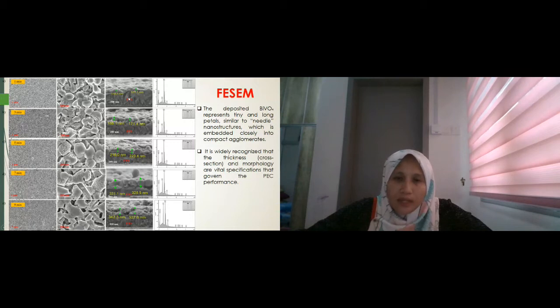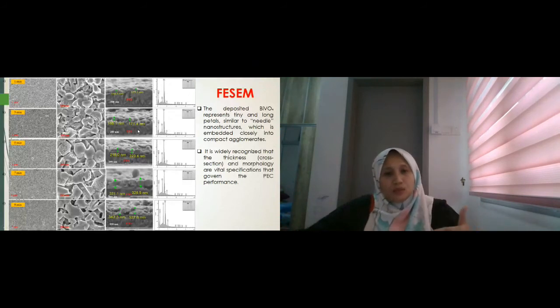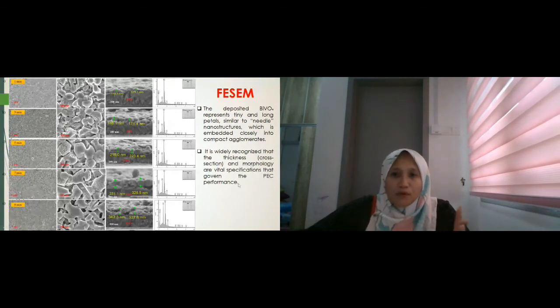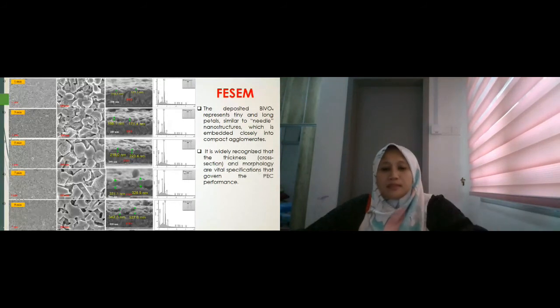This one is the FTO, and then it can be observed that the thickness of the bismuth vanadate will increase. This one, 1 minute, represents around 110 until 121 nanometer. And then after we prolong the deposition time, the thickness will increase until it reaches around 342.5 nanometer. So the cross section and morphology parameters govern the PEC performance.